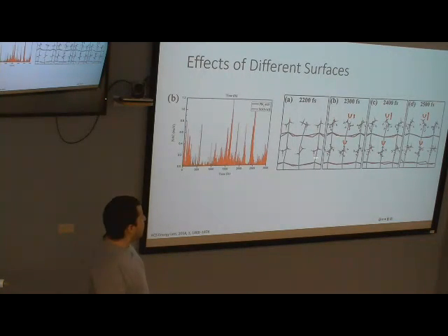So these circles are depicted where they were at to begin off in the 2200, whenever they're seemingly low. There was no non-adiabatic coupling. So you see that the methyl ammonium over time will rotate up, and thus expanding the octahedral cage that they're normally found in, or on the edges. That's really hard to see. You see these points right here. They become flatter right there, so there's probably less distortion on the cage, and that's what's creating these higher distortions of non-adiabatic coupling.